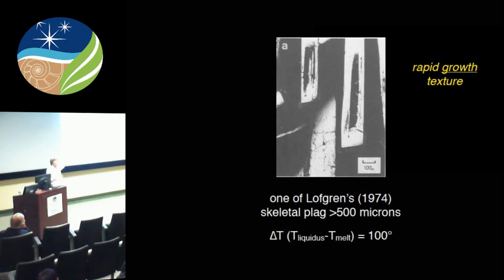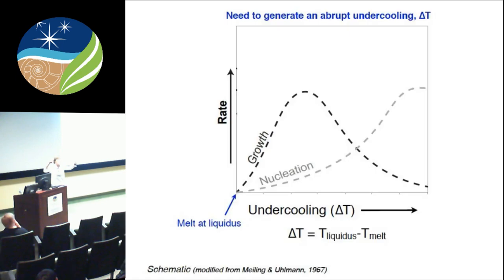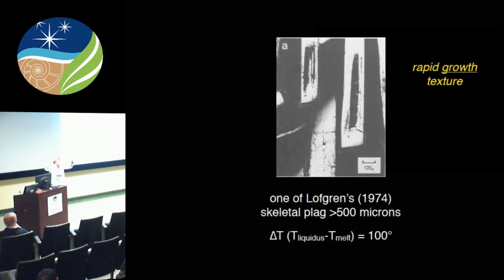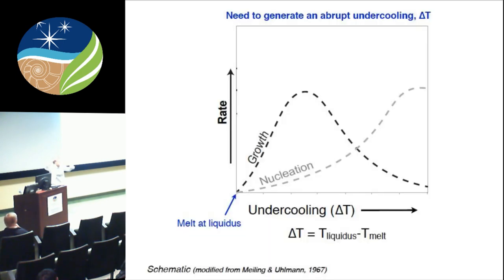So remember I was talking about how you have a magma body that's crystallizing. The interstitial melt, by definition, is on its liquidus. It's at whatever temperature it's at, it is at its liquidus. And in order to get an undercooling, in order to get the temperature of that melt to be below its liquidus, you have to somehow abruptly drop the temperature, like 50 degrees or 100 degrees. And in a magma chamber at depth, it's really hard to figure out how you do that. You certainly can't suck all the heat out by conduction abruptly. So just keep that as a conundrum for the moment.